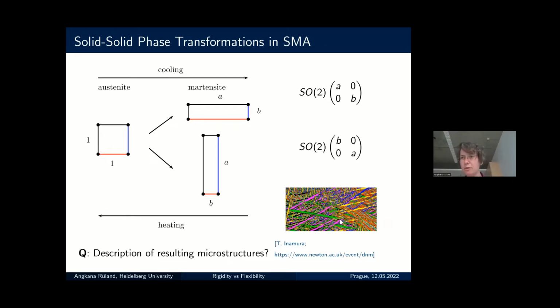You see different colors correspond to different variants of martensite in this situation. You see multi-scale structures. So if you look at this carefully, you see structures nested within themselves, but you also see some kind of order in that these plates, the green ones, are oriented in the same direction, the purple ones are oriented in the same direction.